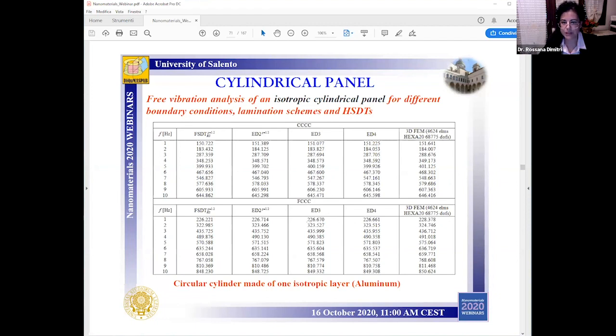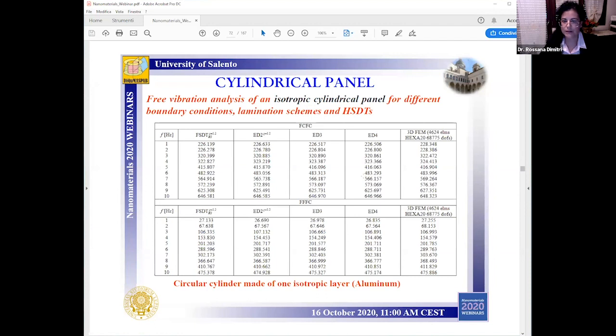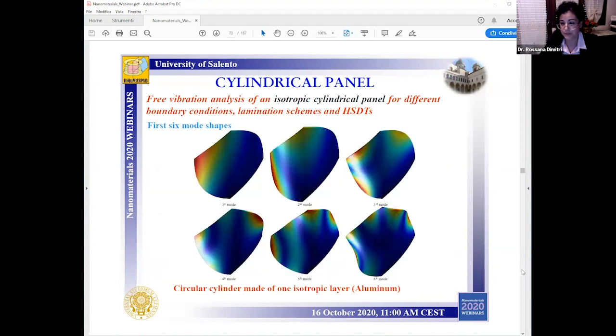So the very good matching between results confirms the high accuracy of the proposed numerical approach, despite the reduced computational cost against the classical 3D FEM-based formulation. As expected, a completely clamped geometry features higher frequency because of the different structure stiffness with respect to the other boundary conditions. So a free clamped boundary condition, where the lowest frequencies are obtained in any case for the same structure with the free edges, as you can see here in the bottom side of the slide, because of the increased structure flexibility.